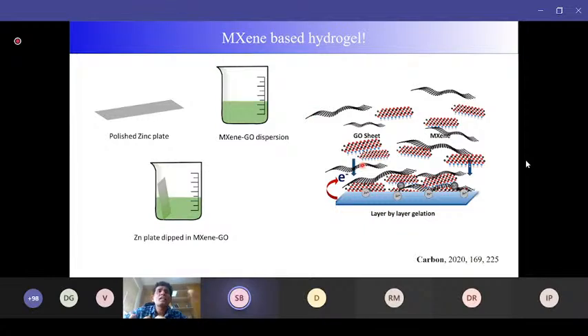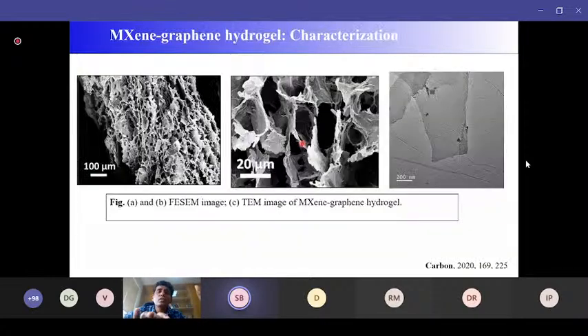They can give the mechanical stability. So we have done exactly a similar strategy, and we have found this structure where it is made of the MXene and the graphene, and you can see that we are getting the porous structure and it's a freestanding structure. And in the TEM image, we can see that these sheets are of MXene, whereas the background, bigger sheets are of graphene.